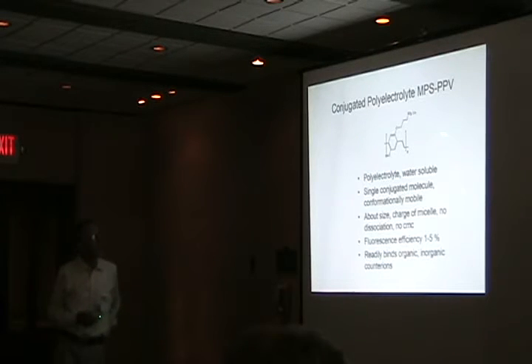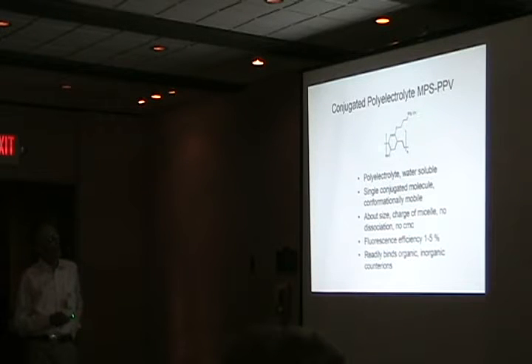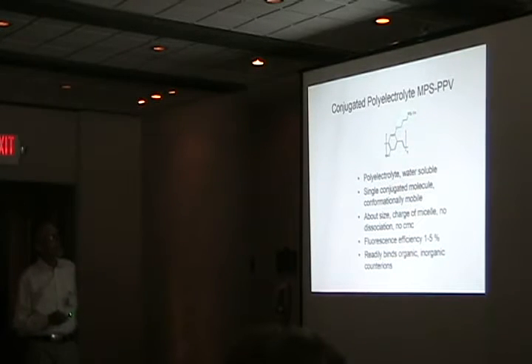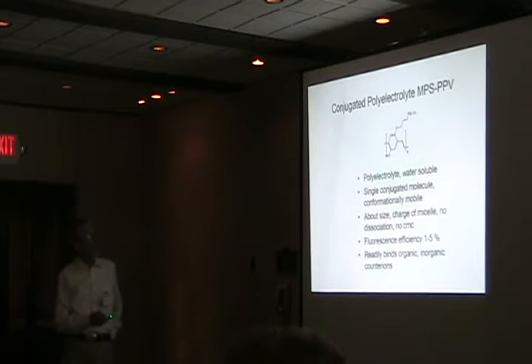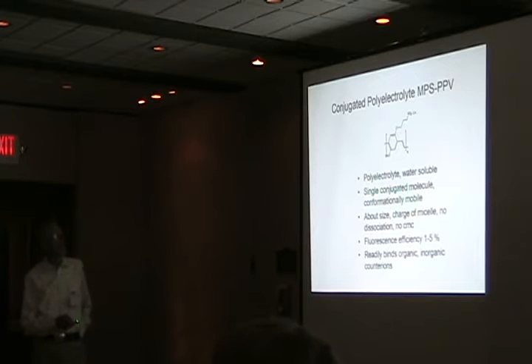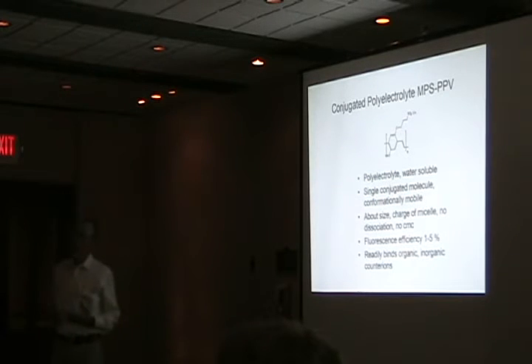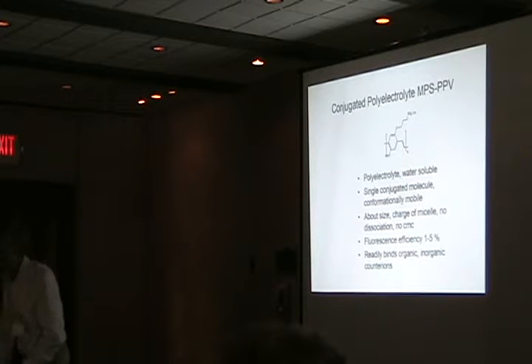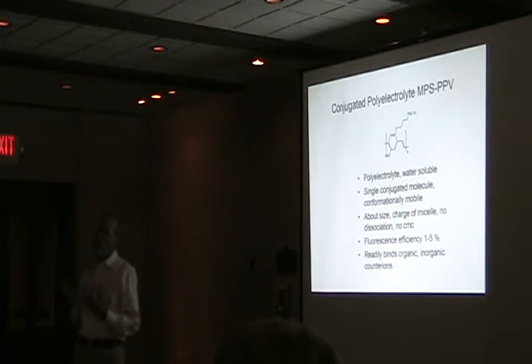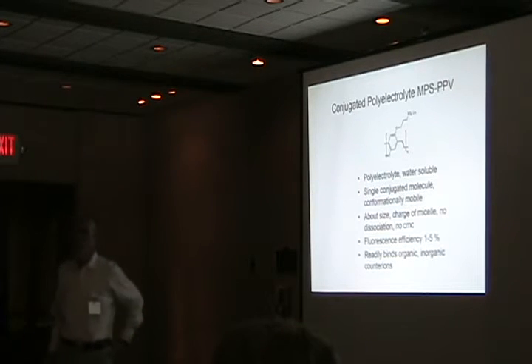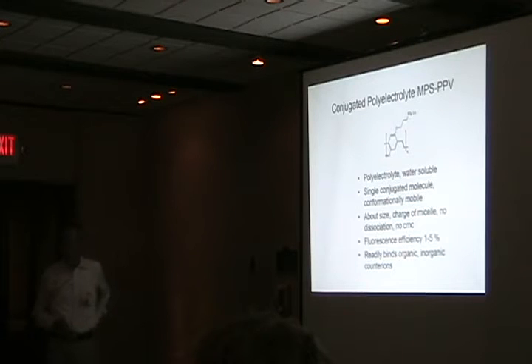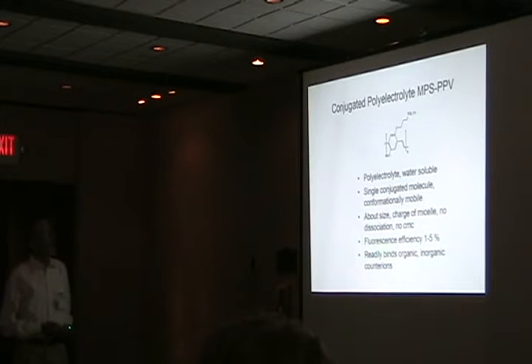Okay, so the first conjugated polyelectrolyte we worked with was this MPS-PPV, and I understand there's still people at Los Alamos working with this. It's a polyelectrolyte, it's water soluble, it's a single conjugated molecule, it's conformationally mobile, and what really appealed to us when we started having an opportunity to work with this is it's about the size of a micelle and has about the charge density of a micelle. And we thought it might interact with counterions. It might associate with them, and that might affect them. And so it does. This has a fluorescence efficiency very low, less than 1% we think in most cases. And of course, like a micelle, it readily binds organic and inorganic counterions.